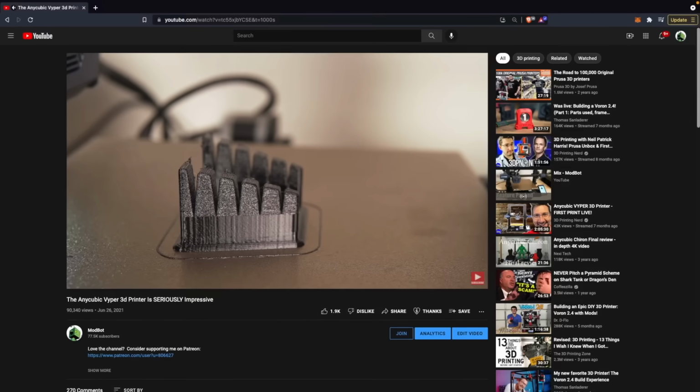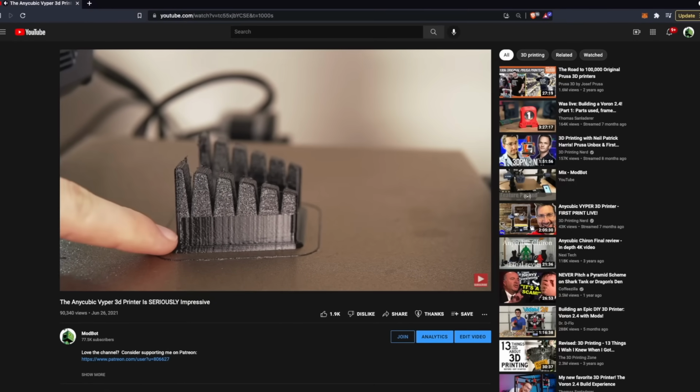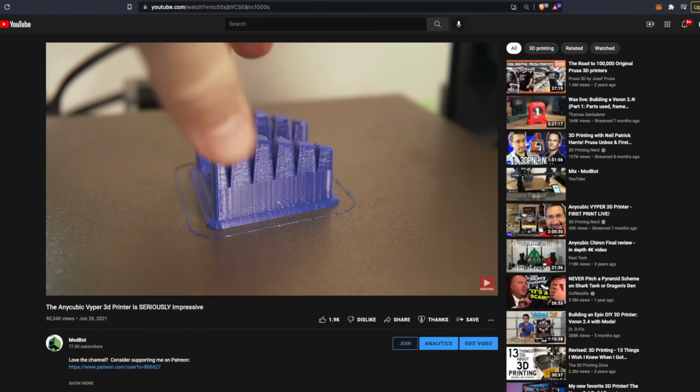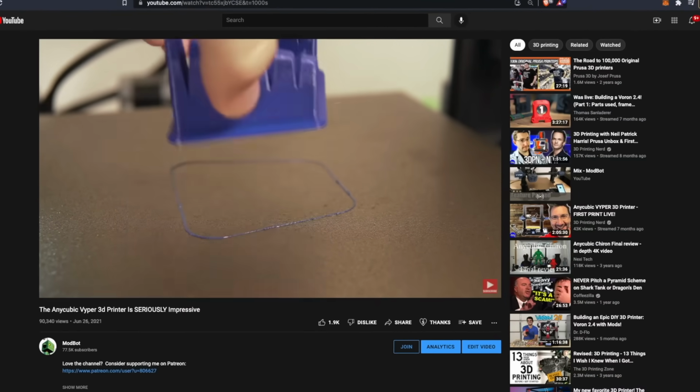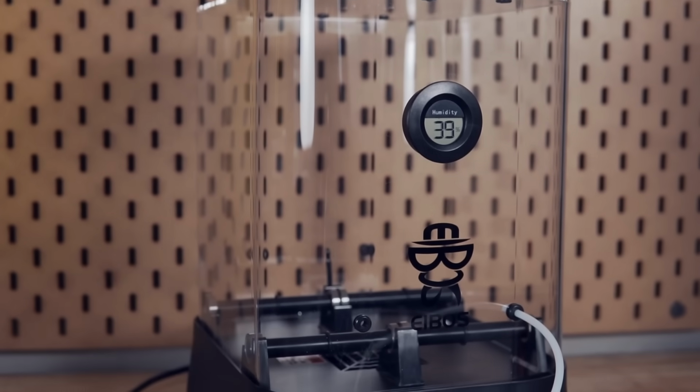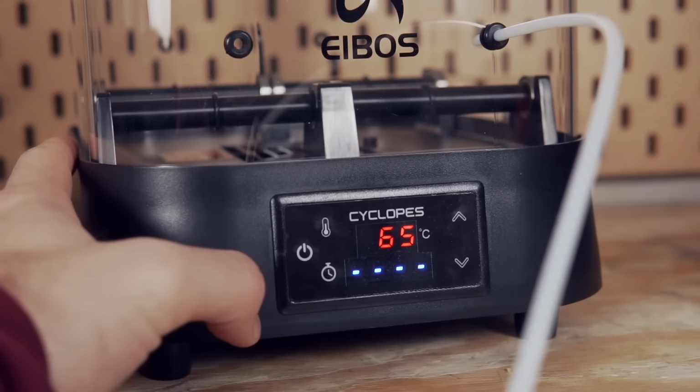One big difference between PLA and PETG is the hygroscopic nature of PETG. I don't think I've ever had real issues with PLA that I've left open for long periods of time, other than that maybe it becomes a bit more brittle, which baking that out will usually resolve. While PETG, I've had a lot of issues with moisture, and it seems to have just gotten worse over the years. So I would say if you're serious about printing with PETG, or really just if you're serious about 3D printing other than PLA, you should have some sort of a drying solution. I know some people use their ovens, some people use dehydrators that they sort of makeshift. I covered a couple options a few months ago at this point.